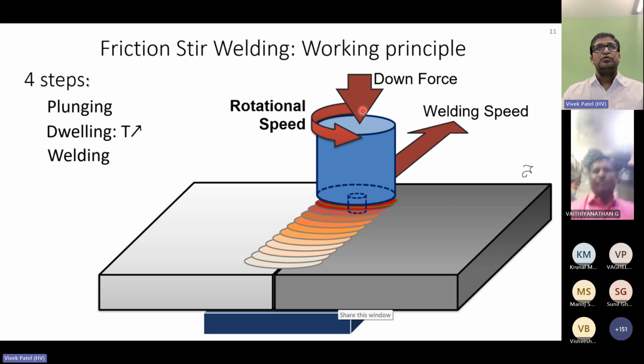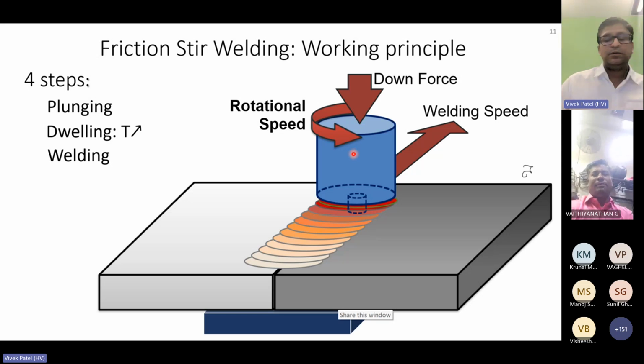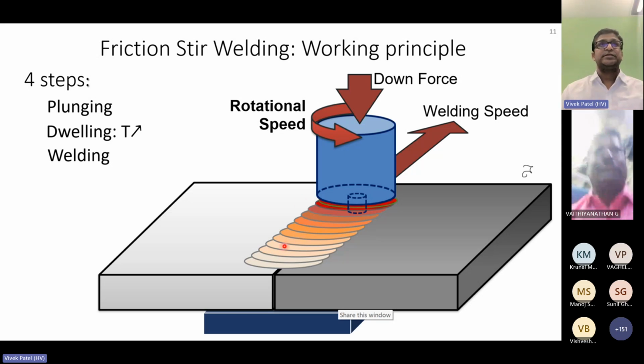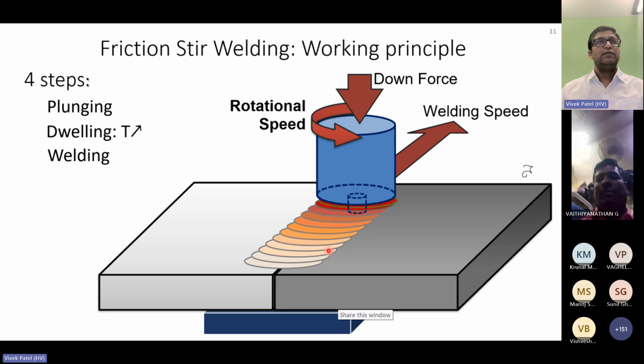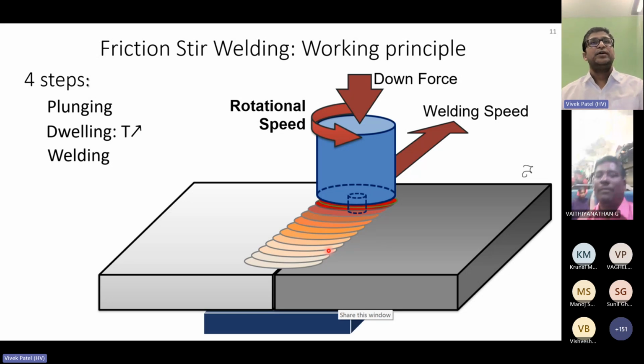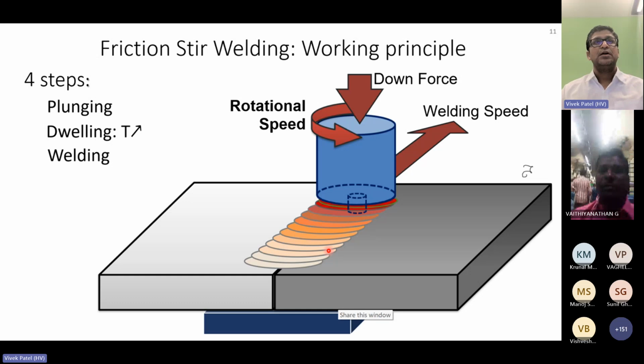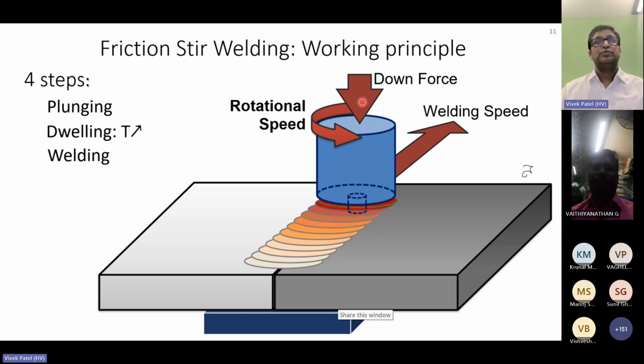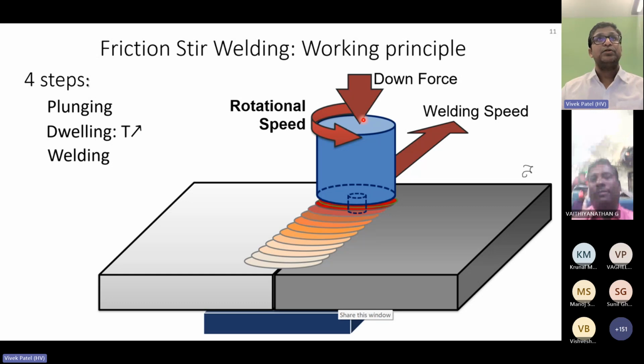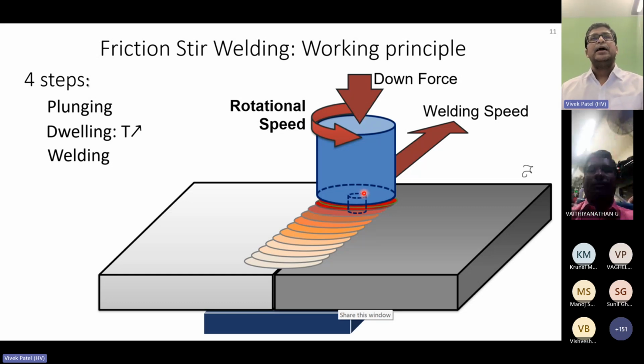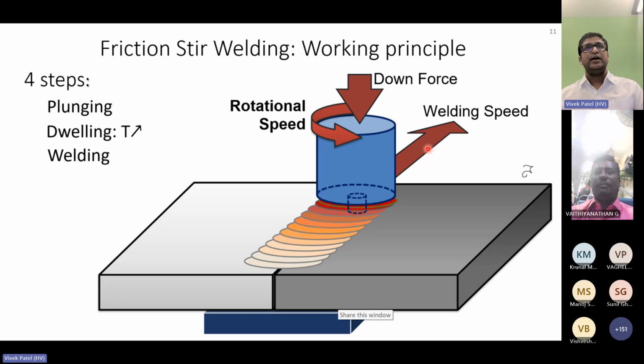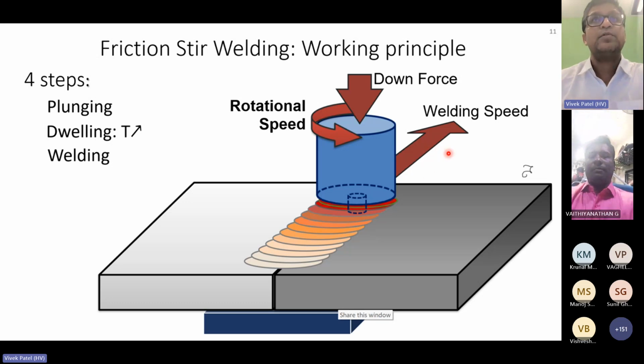Downward force: the amount of downward force basically will decide the surface quality on the weld surface. So if you have less downward force, then you can have some cold defects, or maybe you can end up with a probe failure. So downward force is also very important to decide the right process parameters. And the last is the welding speed, and the welding speed determines the production volume, or productivity.